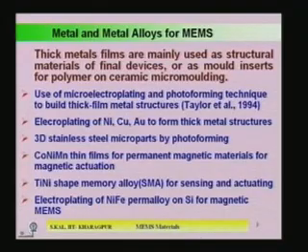Electroplating is another technique which is used for making thick metal films. Thick means several microns, maybe 20, 30, 40 microns, in that range. If you want to deposit more than tens of microns, then the conventional thin film evaporation or sputtering technique cannot help. With those techniques you can get films of the order of maximum 2 to 3 microns, and if you want 10, 15, 20 microns, then you have to adopt certain techniques. Those are mainly the CVD techniques and the